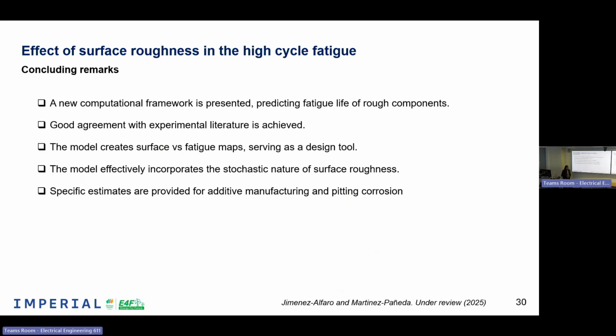So just to finish, I would like to give you some concluding remarks. First of all, we have developed a computational framework that is able to predict the effect of rough surfaces in fatigue life of any kind of specimens. We have shown you that there is a good agreement, both qualitative and quantitative, with experimental data. We have built some operational maps where we have faced the surface versus the fatigue effect. And this is good because we can propose these operational maps as design tools so that people can design their specimens or their materials following these operational maps. And what's interesting is that the model is including the effect of randomness, that is a natural effect in the surface roughness, inside the model. And although we have this, we are obtaining reliable results.